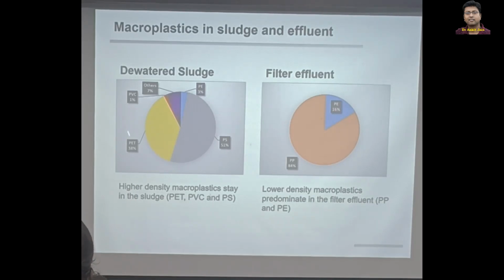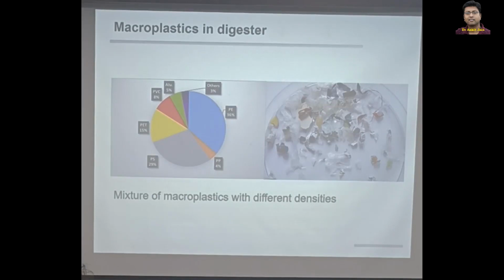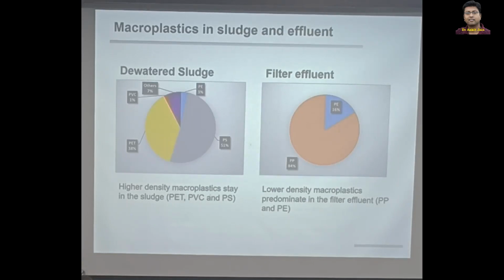In the sludge, you have the plastics that are heavier. For example, you have the polystyrene, the PET, the PVC, the PE. These ones here below are heavier plastics and they stay in the sludge. And we quantify the percentages of both. We also quantify directly the plastics in the digester, the different types, as you see, and it's not very different from the plastics in the water sludge.